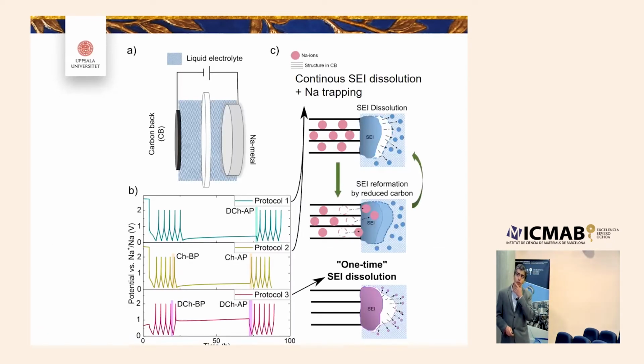Since then, we have been using many different cycling protocols and many different battery systems. As I said, we have been using carbon black as a model system with high surface area to generate a lot of SEI and accelerate SEI dissolution, but we have also been testing hard carbon and metallic gold and metallic platinum as the negative electrode substrate.